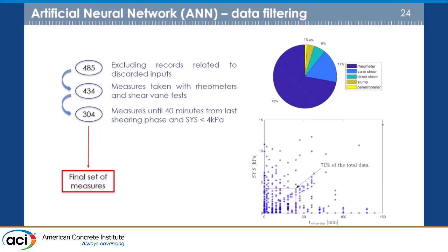The other thing important for 3D printing is the time frame over which the yield stress parameter has been measured and where this time frame starts. From the contact of water with the powders is what we agreed upon. But we found, going through the papers that contained this information, that about 70% of the data had a record in the first 40 minutes, which we deemed reasonable for a 3D printing application.